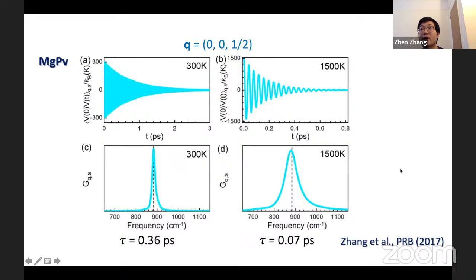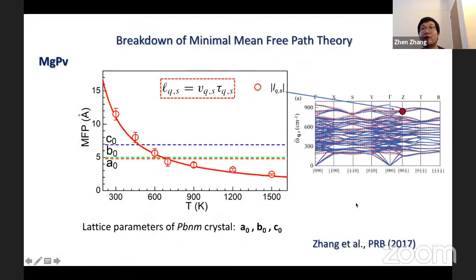Here, for magnesium perovskite, we collected the temperature-dependent phonon lifetimes from phonon quasiparticles. We can see that as temperature increases, the VAF decays faster. The corresponding power spectrum exhibits wider line width, indicating that the phonon lifetime depends inversely on temperature. Phonon lifetime decreases as temperature increases. Therefore, at sufficiently high temperatures, the phonon mean free path can be lower than the lattice parameters, and no saturation behavior of the mean free path or the kappa was observed. Also, the mean free path roughly obeys the 1/T law.